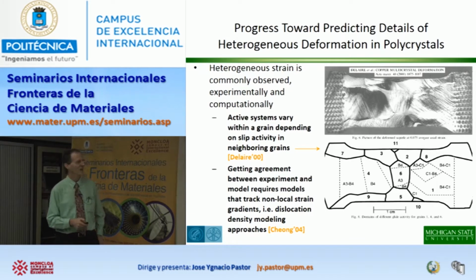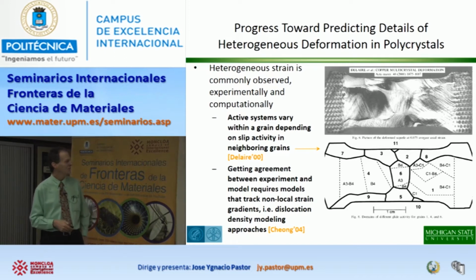So here's an interesting example of heterogeneous strain in a copper multicrystal. It's not a polycrystal because there's only a few grains in this sample. It's grown to be a big grain size. And people who studied this some time ago observed, interestingly, here's a great big grain right here, but in different regions within this grain, there are different patterns of slip that are present in different areas. So that means the slip in one part of the grain can be really different than the slip in another part of the grain, according to how the boundary conditions of the neighboring grains are deforming, which makes it really complicated. So can we figure out how to handle that complication?